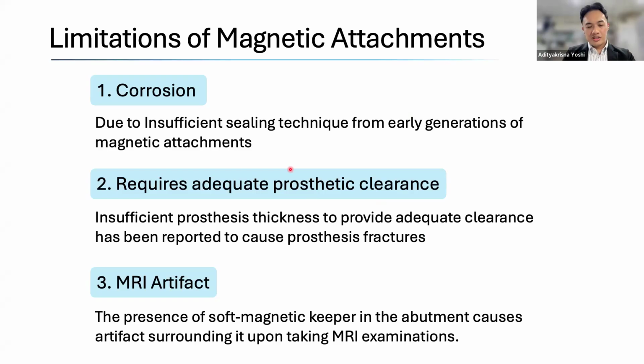From my previous slides, we can see that in the past, magnetic attachments had some limitations or problems. The first one was corrosion, which was reported before the 2000s. It was mainly because of the insufficient sealing technique in early generations of magnetic attachments. The other limitations include requiring adequate, thick prosthetic space clearance. It was also often reported that the keeper cemented or fixed onto the abutment tooth or the implant inside the oral cavity can cause magnetic resonance imaging artifact.